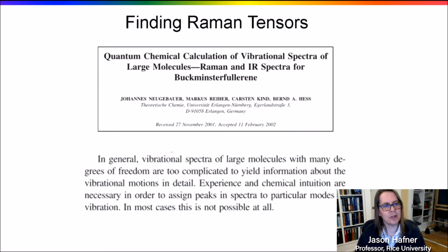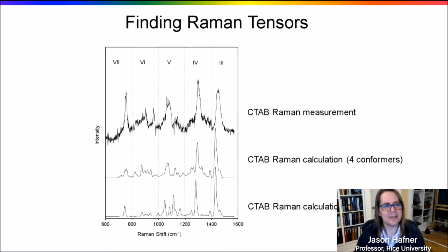So the next slide, I'll show you an example of, again, CTAB. We really haven't done lipids. I keep showing CTAB results. Here is the Raman spectrum of CTAB with several peaks. And we definitely know what this one is. That's the head group. And some of these we kind of know because it's an alkane chain. But this is how powerful that DFT method is. This is the match for a single CTAB molecule. But that's with a straight chain. So that's a pretty good match.